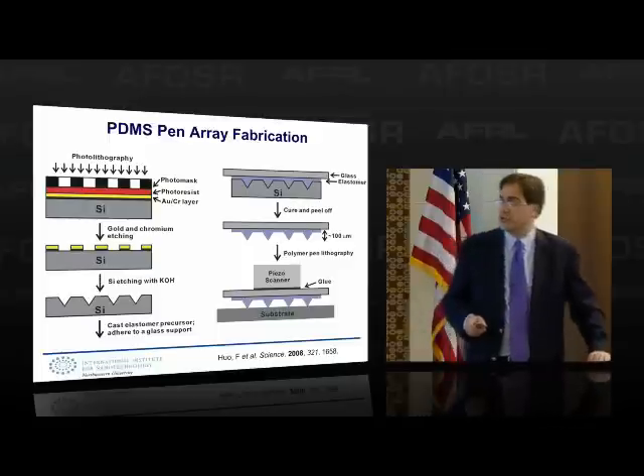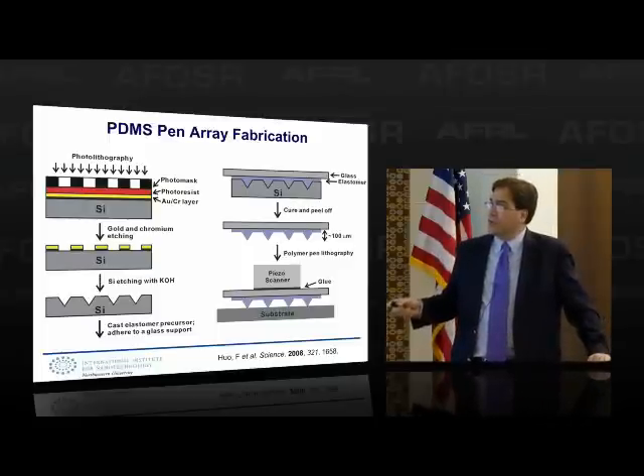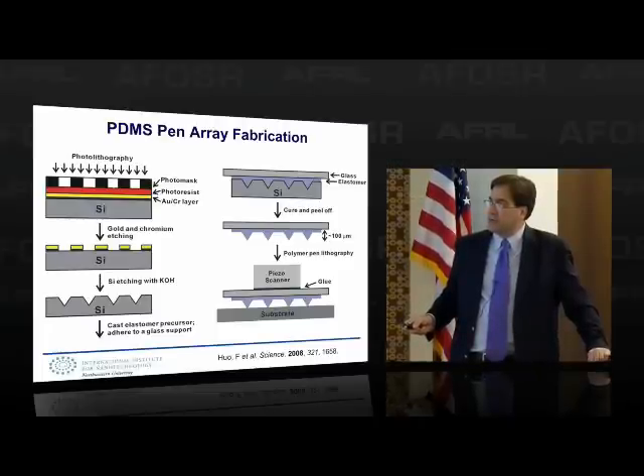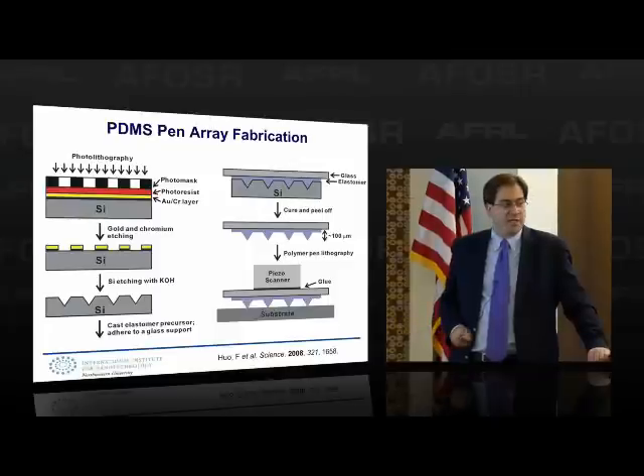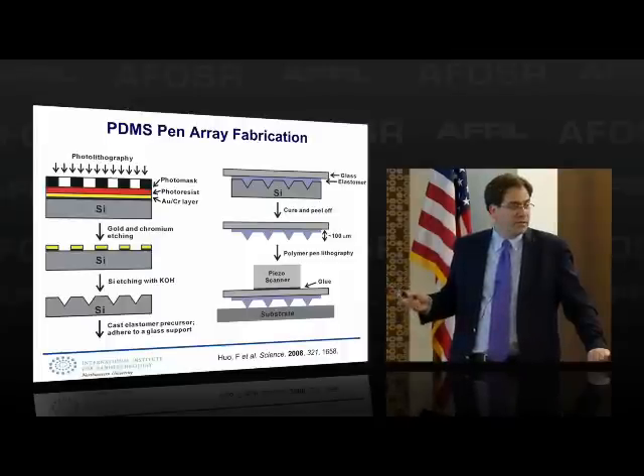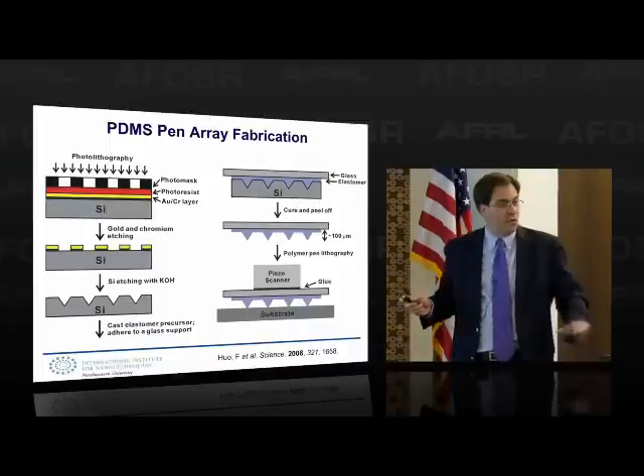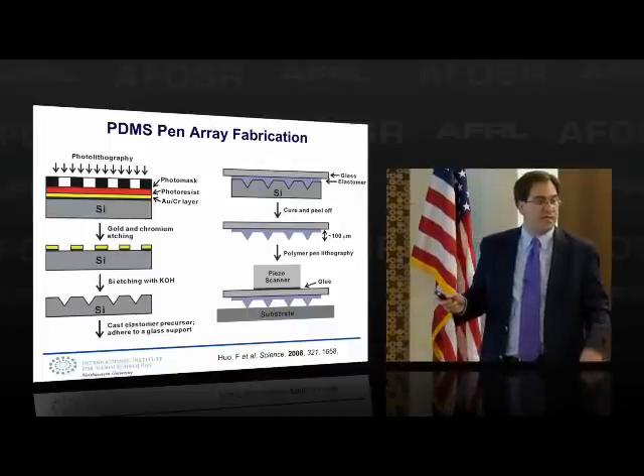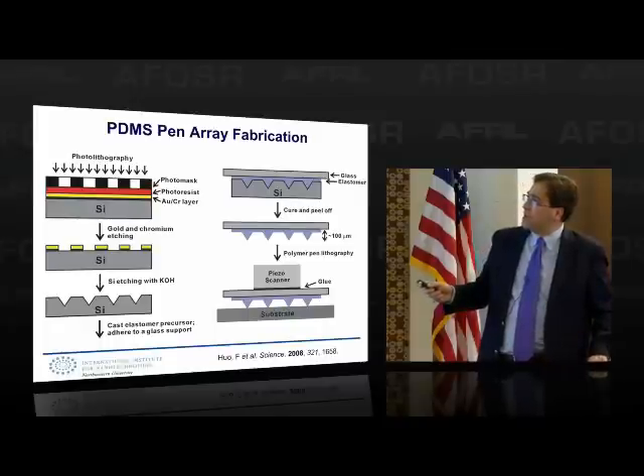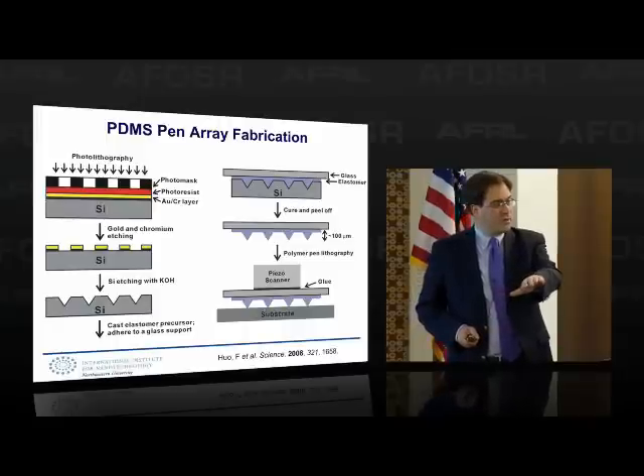So this is how you make these structures. Pretty simple. You use ordinary photolithography to make a master. You just make a series of holes in the resist. You then etch the exposed silicon with KOH. It's an anisotropic etchant that naturally gives you these pyramidal pits. You then pour in an elastomer, put a transparent slide over here. That's important. A hard backing that's got to hold this. So you couldn't just use it as a stamp, for example, on a micro-contact printing type of experiment. That wouldn't work.